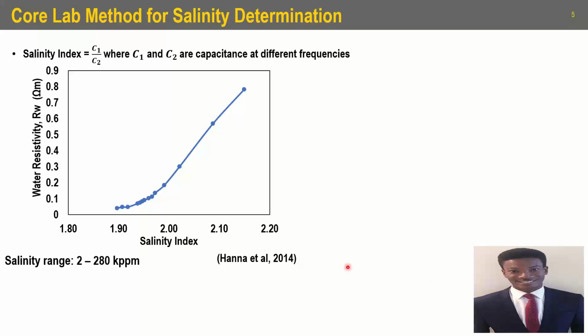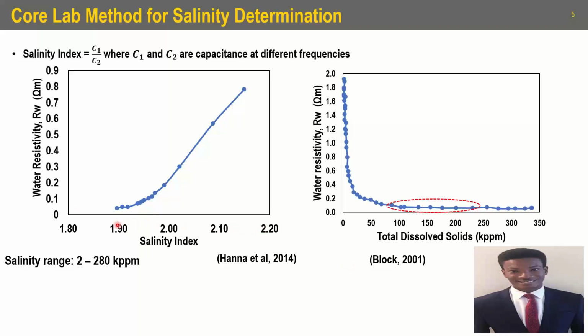And one of them is that we see that the salinity index covers a very low range, that is from 1.9 to about 2.15. That's about 0.25 range, and that is for a salinity range of 2,000 ppm to 280,000 ppm. So the salinity index range is pretty low for the water resistivity values that we would be interested in.